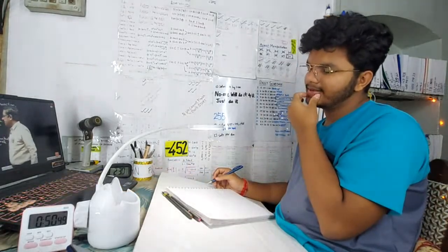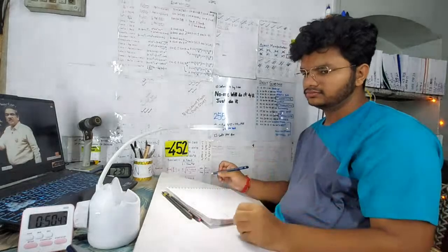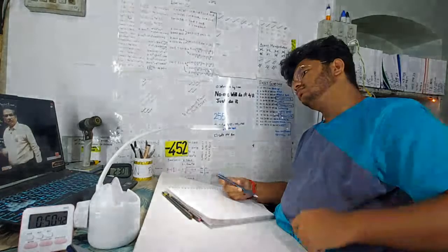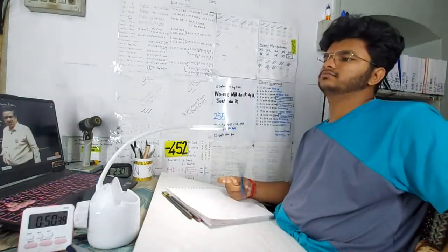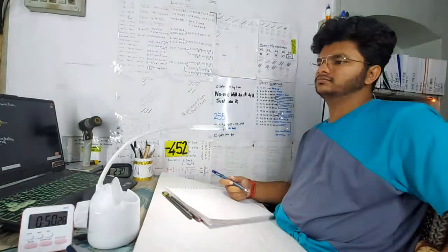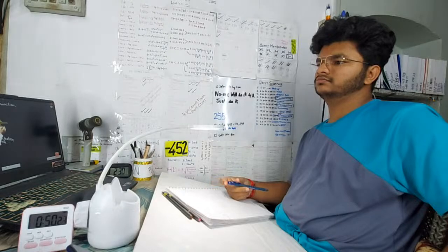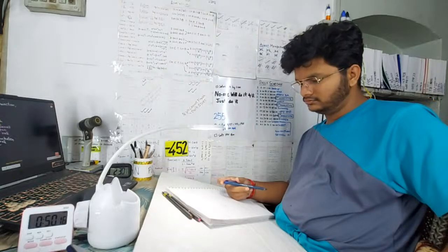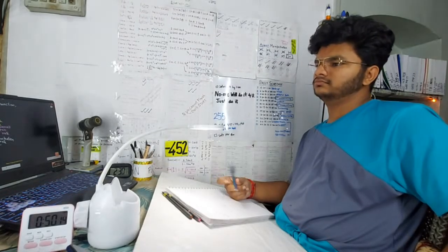Second conclusion is that if you want to plot, the overall transformation rate is always the product of these two. The product of growth rate and nucleation rate gives you what is called the overall transformation rate. Therefore, if you would like to plot that, let us say for example, this is the product of these two. When plotted at every temperature, the variation of overall transformation rate will be like that. So this graph is showing overall transformation rate. Overall transformation rate is obtained as the product of growth rate and nucleation rate.